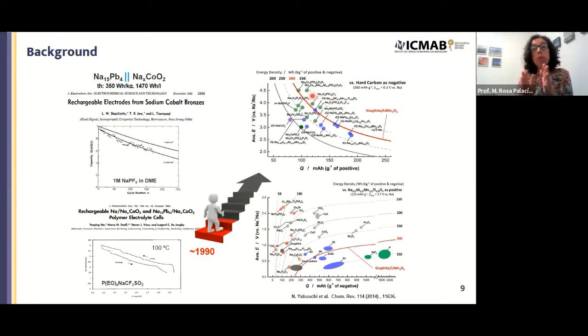So if you did a full cell with those positive electrode materials and hard carbon, these are the energy densities that you would get. And here you have as a comparison the graphite lithium manganese oxide, which is also a commercial lithium-ion technology. So you see that for many materials, the energy density would be on par with commercial lithium-ion batteries. And here is the complementary graph.